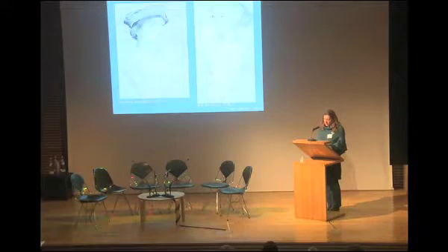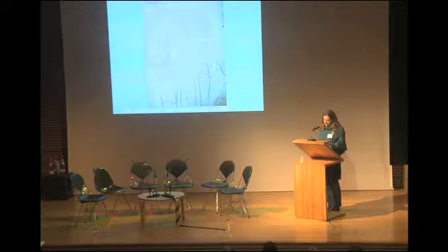Richard Southwell and Jane Seymour are examples of Holbein's use of pink prepared paper covering the entire sheet. They illustrate the difference in the makeup of the batches of the preparation, depending on ratios of materials as well as how it is applied. Raman analysis of 18 Windsor drawings confirmed Holbein's use of vermilion and calcium carbonate in the composition of these preparations. In the case of Southall, the pink preparation has obvious brushstroke streaks seen in its application, and is a thinner, more watery tint than the more opaque examples.